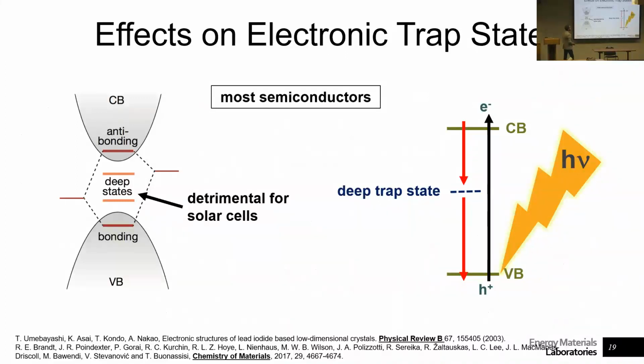That's basically what I'm trying to say with this graph: most semiconductors are defect intolerant. You put in any kind of defect and you create trap states in the middle of the gap. Here we have a valence band and a conduction band. A photon comes and photo excites an electron into the conduction band. With an electric field, we want that electron to be extracted out of the conduction band as soon as possible, without losing its energy. But if you have a trap state in the middle of your band gap, the electron has an incentive to go there, because it's easier to go into this state than go across 100 nanometers of material. So this deep trap state collects an electron.